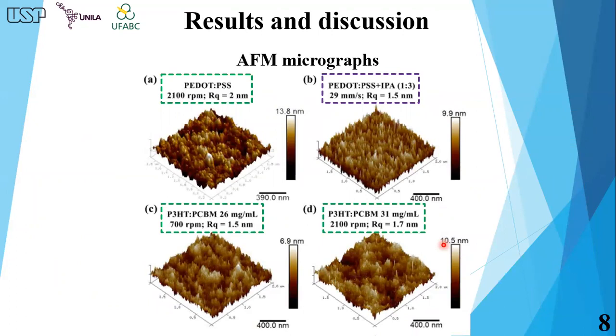The four pictures were obtained using atomic force microscopy. A and B show decreased roughness of the films when PEDOT:PSS is diluted in IPA and deposited by blade coating. C and D show that in solution with higher concentration, the roughness increases. Reduced roughness is expected to prevent short circuits between different layers in the organic solar cell structure.